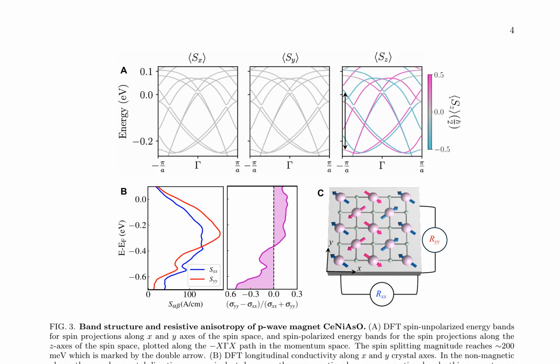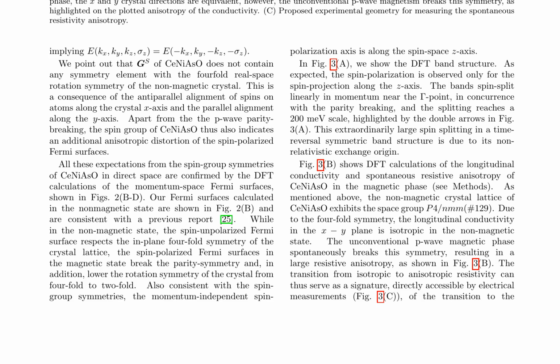The DFT calculations show a spin unpolarized energy band for spin projections along the x and y axes and spin polarized energy bands for the spin projections along the z axis. The spin-splitting magnitude reaches approximately 200 meV. The paper also discusses the resistive anisotropy of the material, which is a direct consequence of the unconventional p-wave magnetism. The transition from isotropic to anisotropic resistivity can serve as a signature for the transition to the magnetic phase, accessible by electrical measurements.